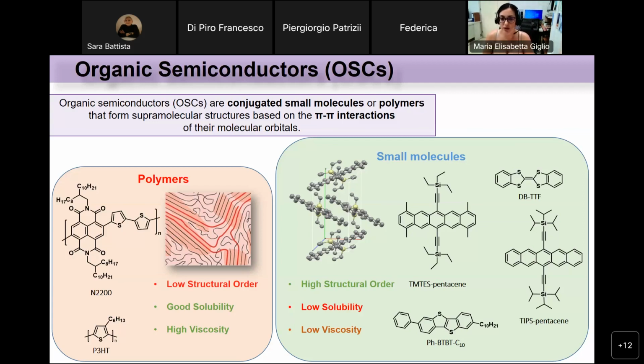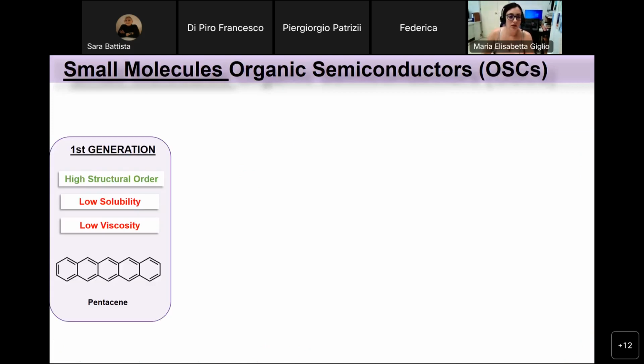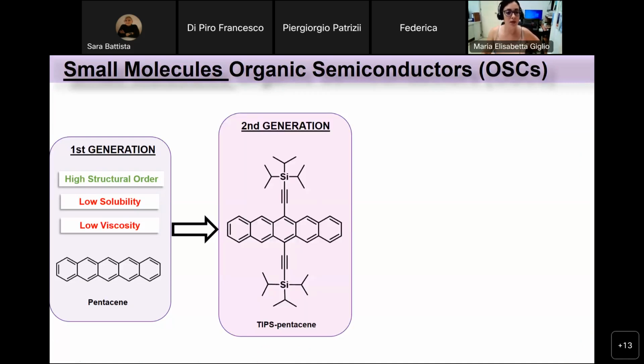And then on the other side, we have small molecules, which we are particularly interested in in our group, that have very high structural order, and they crystallize very well. However, the majority of them are affected by low solubility or low viscosity. The first generation of small molecule organic semiconductors is represented by pentacene. Pentacene, for example, has a very high level of structural order. However, it has low solubility and low viscosity in solution.